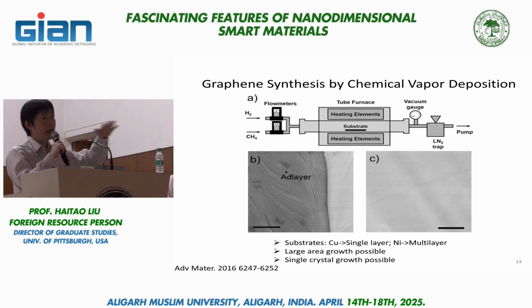So this approach can give you a large area of single layer graphene. We're talking about centimeter square, and even in some cases, much larger ones approaching meter square in size. You are using a continuous roll of copper foil as a substrate. And those graphene are of much higher quality. They can be made almost defect-free, and in some cases, they can be made into a single crystalline structure. So one piece of graphene is a single crystal up to centimeter size domain size, and that can be done by using a single crystal of copper as the substrate.